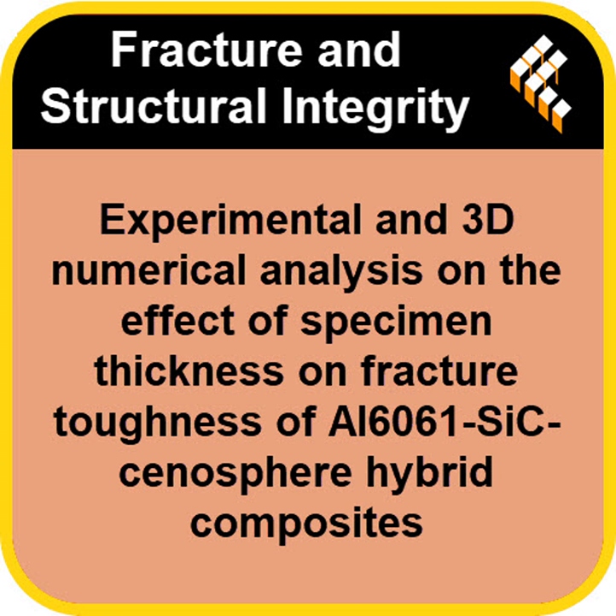So how did they actually make this tricky hybrid material? You've got light aluminum, dense SiC, and these hollow cenospheres. Sounds like they'd want to separate. Yeah, it's not trivial. They used a method called stir casting. So they melt the AL6061 base aluminum. Then they introduce the reinforcement particles, the SiC and the cenospheres. But crucially, they first meticulously preheated both types of particles. Preheated to what? To 350 degrees Celsius for about an hour before adding them to the molten aluminum.